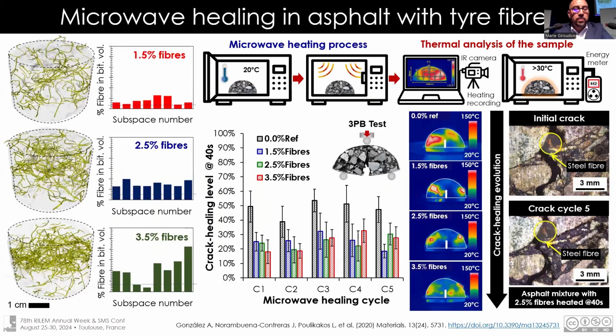At the same time, we can use tyre fibers to stimulate the materials, but the recommendation is that this fiber is so complicated to work with because it's necessary to make several modifications in the mixing process to obtain a very good asphalt mixture. But it's possible to heal the samples.